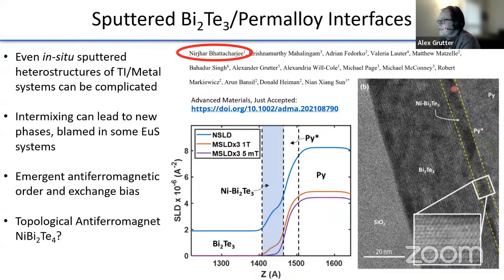But what they found that was really interesting is that you have to pay a lot of attention to the surface chemistry in this system as well. So it's not just looking at low density interface regions, but if you grow, say, bismuth telluride next to permalloy or some other ferromagnetic metal, you may actually get a distinct intermixed region like you see right here.